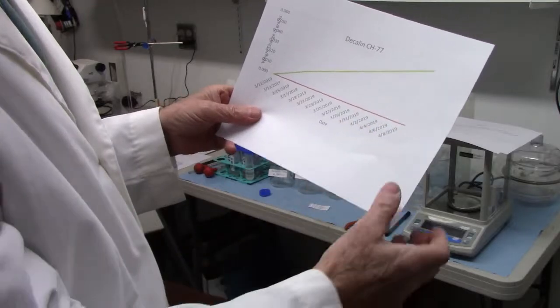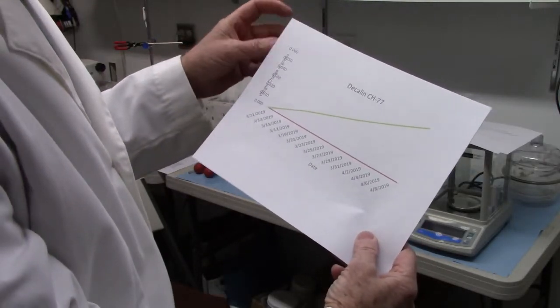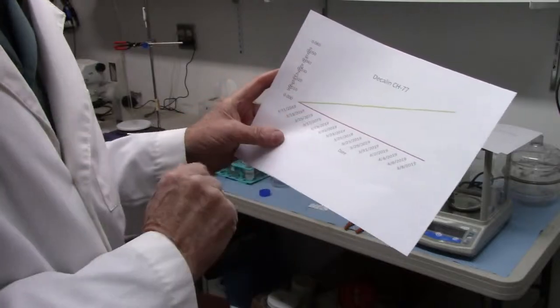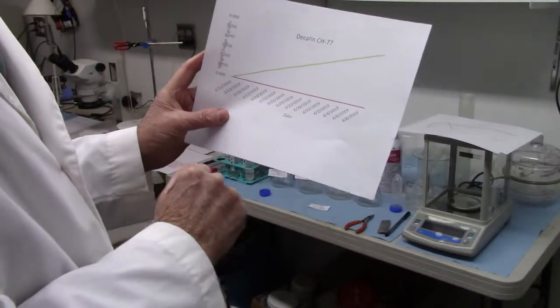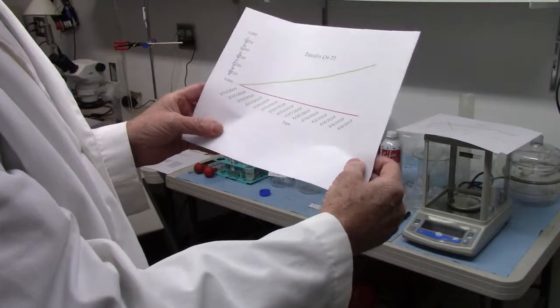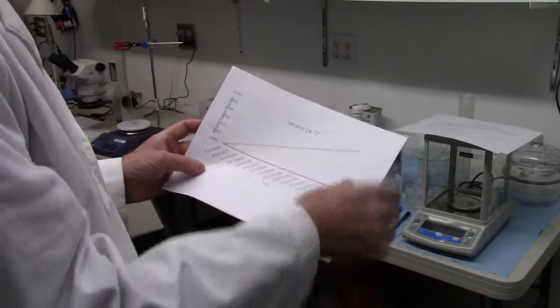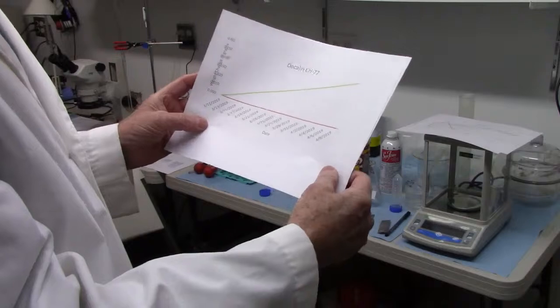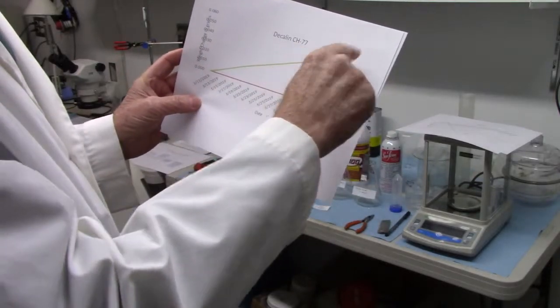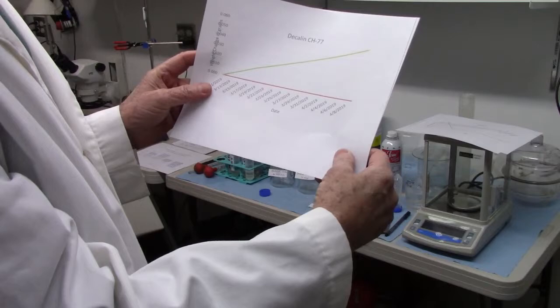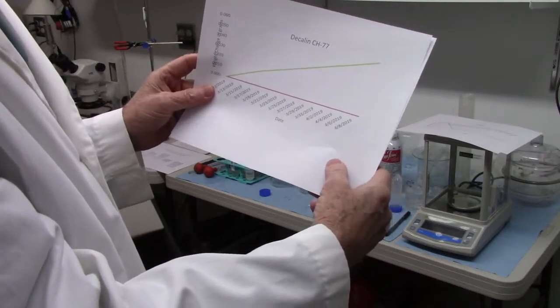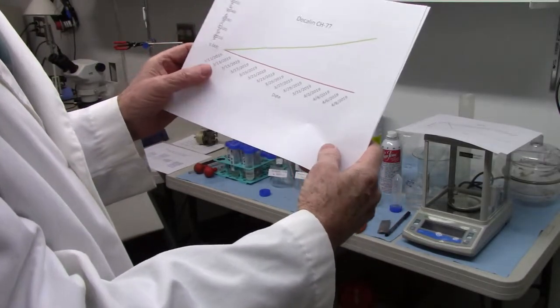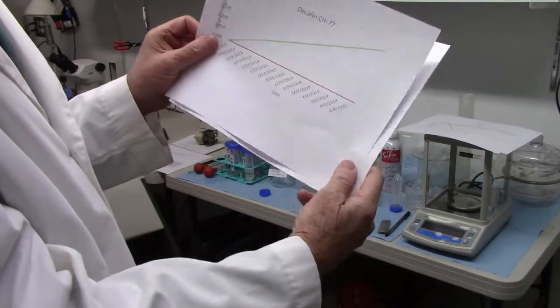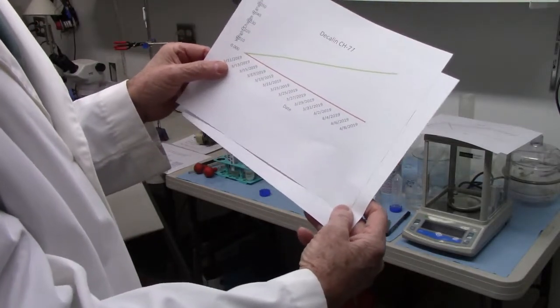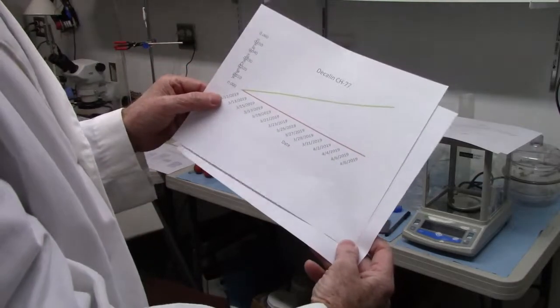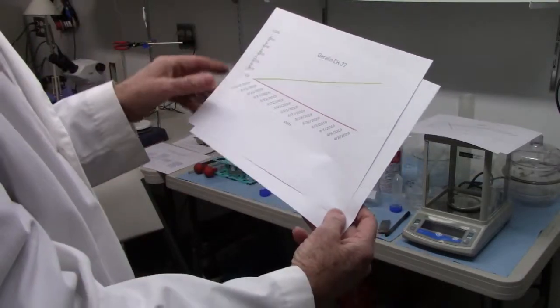So what was building up on the surface, and remember I wiped off the surface before I did the weighing so that the corrosion was not weighed with it, that is, those white deposits. It gradually increased in weight. I could surmise that the thickness of the protective layer was gradually increasing over time. Certainly the coupon was not decreasing in weight, and it didn't visibly look any thinner. This is in seawater, remember.